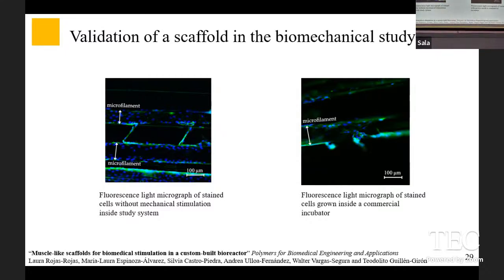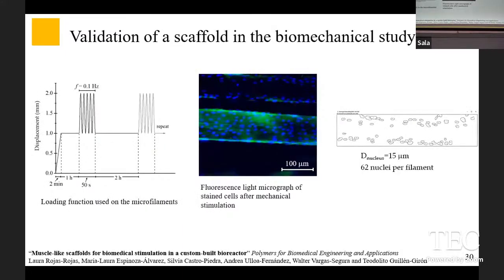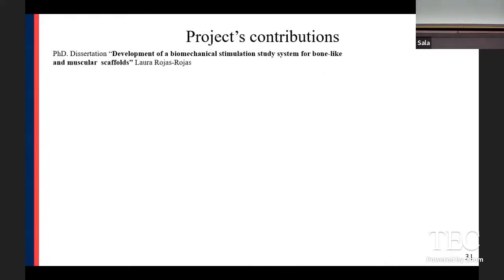Now, in addition, we wanted to do one final test, and for that, we decided to do a loading on the scaffold, because this is what the bioreactor should do, the system should do loading. So we selected a loading function that we found in literature, and also we had a very good result because cells remain on the filament and withstand the loading. And now we are trying to get interesting results such as cell counting and the nuclei distribution on the samples. So with that, I would like to show you the project's contributions.